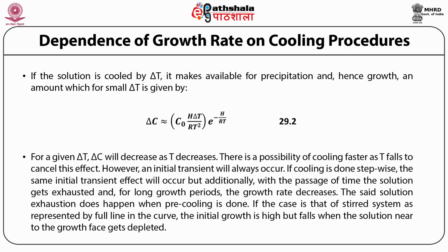For a given delta T, delta C will decrease as T decreases. There is a possibility of cooling faster as T falls to cancel this effect. However, an initial transient will always occur. If cooling is done stepwise, the same initial transient effect will occur, but additionally, with the passage of time, the solution gets exhausted, and for long growth periods, the growth rate decreases. The said solution exhaustion does happen when pre-cooling is done. If the case is that of a stirred system presented by the full line in the curve, the initial growth is high, but falls when the solution near the growth face gets depleted.